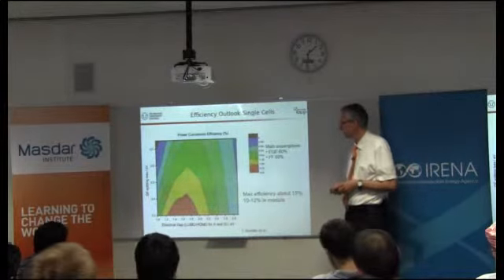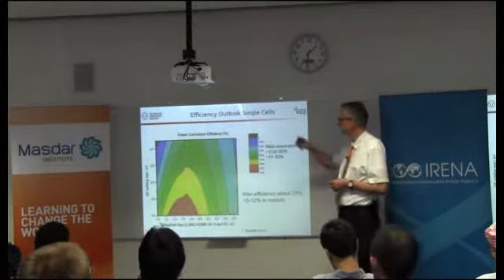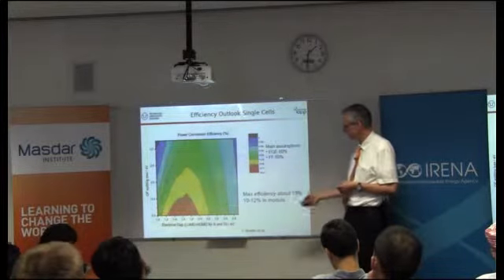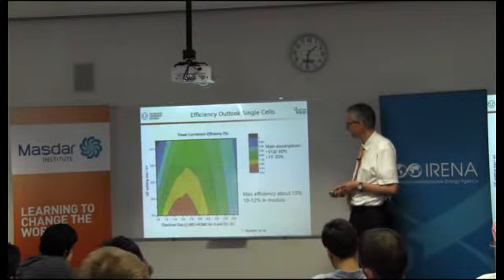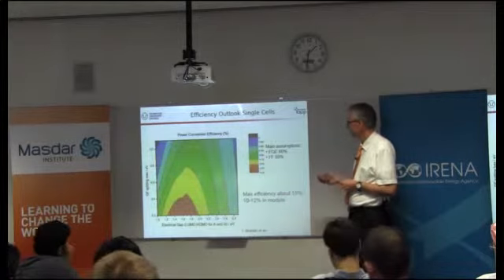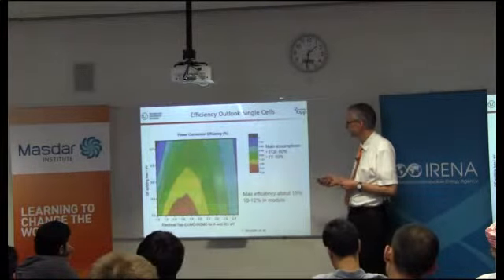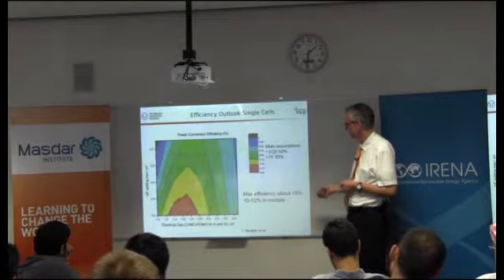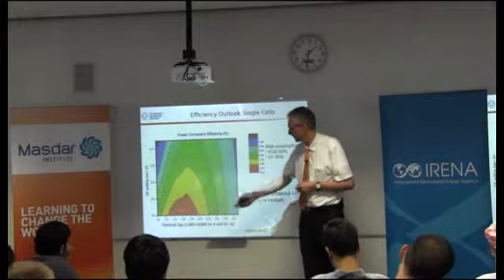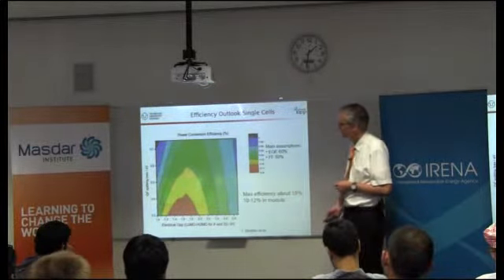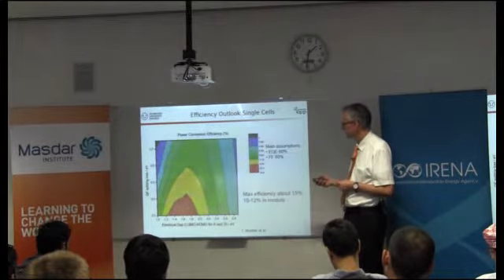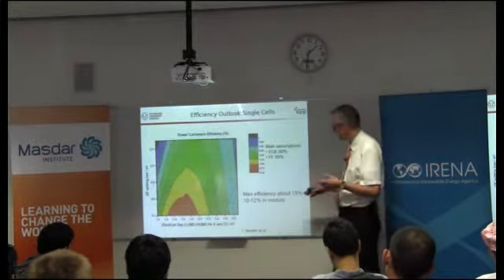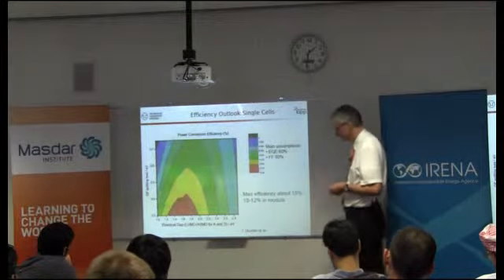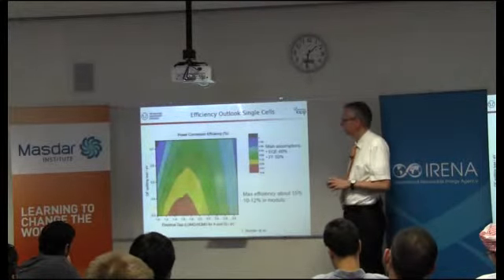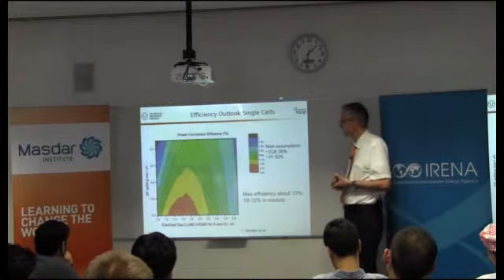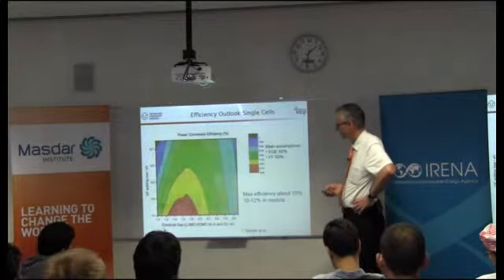Now, when you calculate the efficiency for single junction solar cells, that's a calculation done by a PhD student of mine, you basically end up with an efficiency in the range of about 15% here. If you have the optimum gap, then you end up with about 15%, which means that in a module you would expect 10 to 12. And that is too little. So obviously, if you do organic solar cells, single junction, you have a problem.